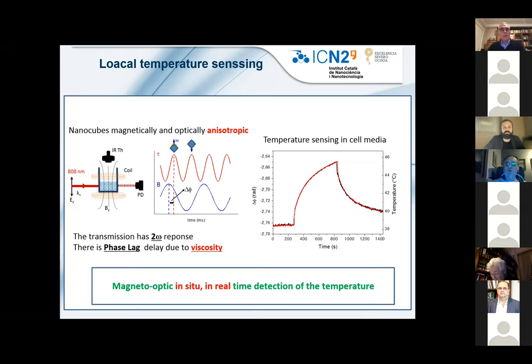Yeah, yeah. What we do is calibrate using the cell media, using a Peltier, and using the infrared thermometer very slowly. This here is not fast, but this is really fast. There we can change the temperature very slowly, so the infrared thermometer and the nanoparticles measure exactly the same temperature. Yeah, I see. When you do it fast, the infrared thermometer only measures the surface, and the heat cannot reach the surface at the same speed as it hits inside. That's why the nanoparticles are more accurate in measuring the inside of the cell media. But first we calibrate using a slow Peltier measurement. Thank you.